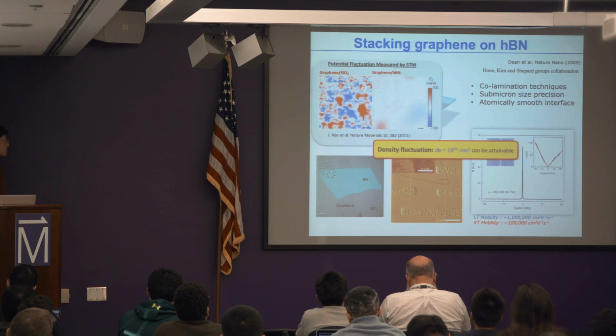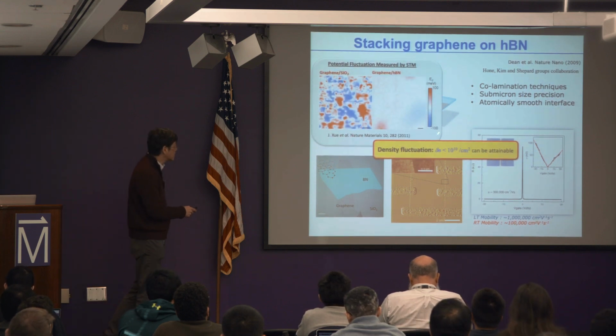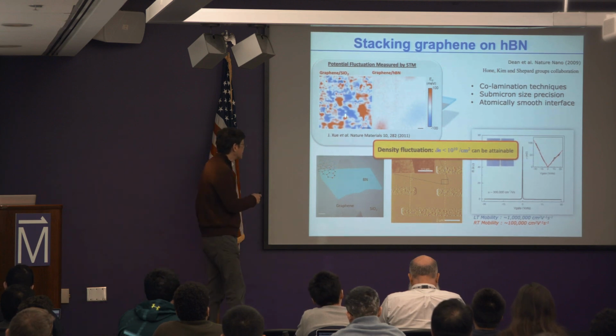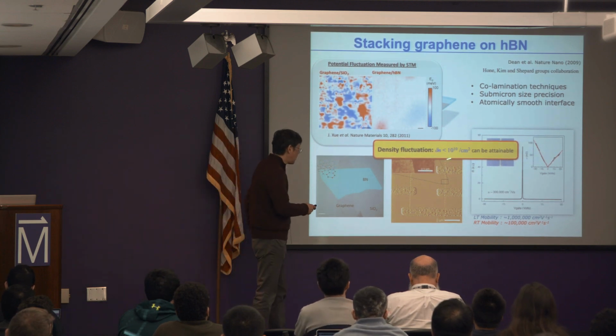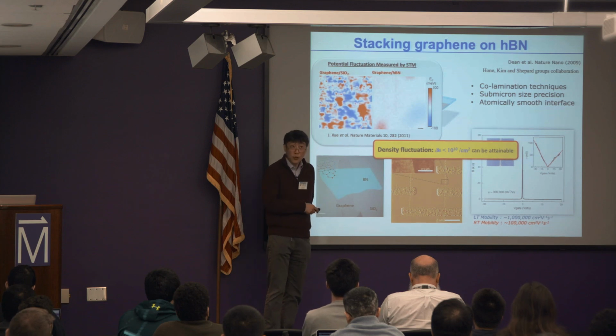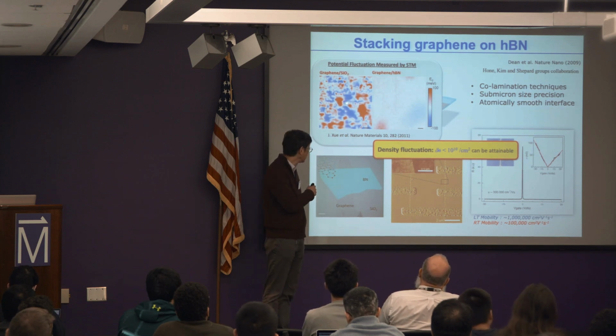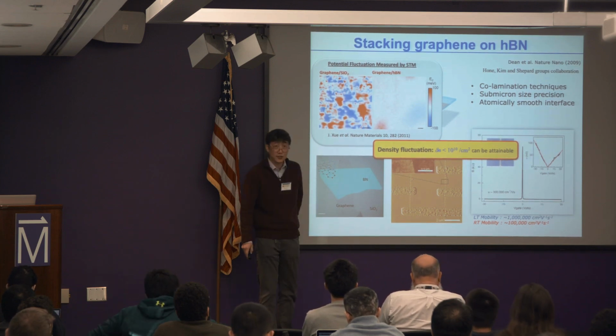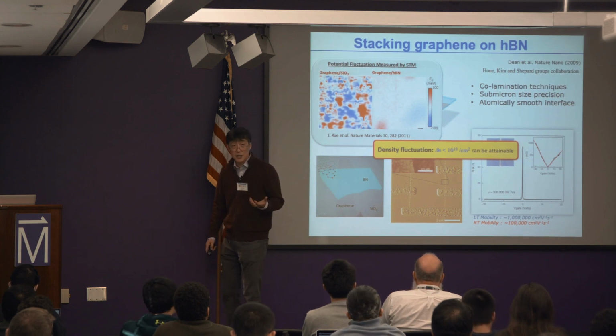One thing about this type of sample is that when you measure the Dirac point variations, the residual density in the electron-hole puddles is now almost two orders of magnitude smaller than what it used to be. So it is less than 10 to the 10 electrons per square centimeter.